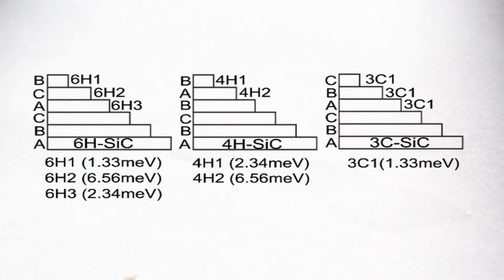So they don't form two-dimensional layers over the whole surface, they are ribbons, and so on. So from a research point of view, this is very exciting. And in silicon carbide, when you do silicon and carbon atoms, you can stack them in different ways. You have the hexagonal ones, the 6H silicon carbide, the 4H silicon carbide, but also the cubic silicon carbide, which is very difficult to grow because it's metastable. But they have some different stacking sequences and some differences in properties.